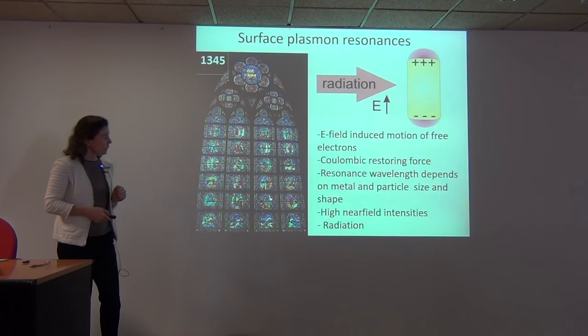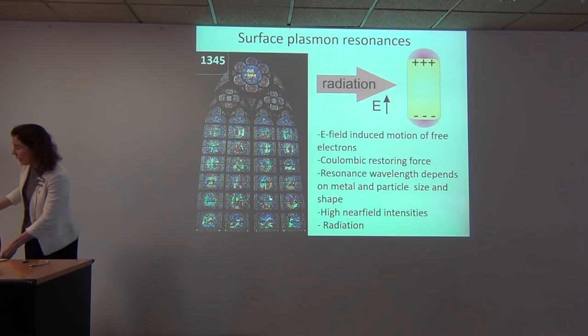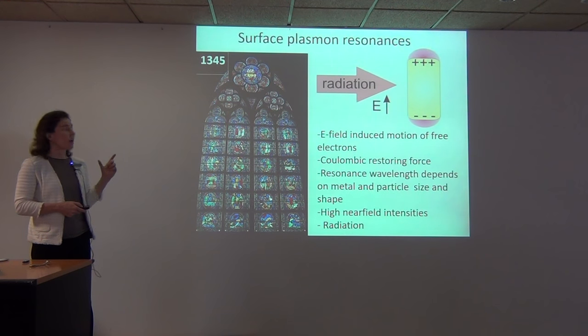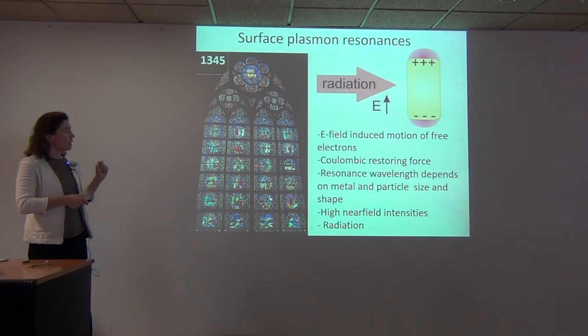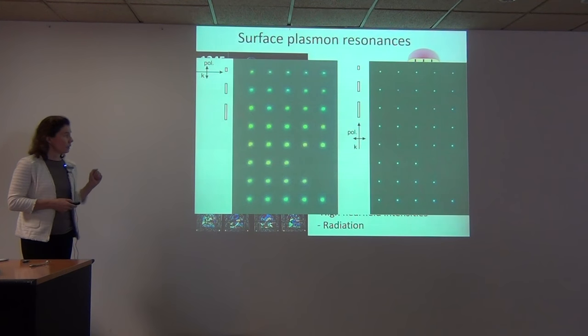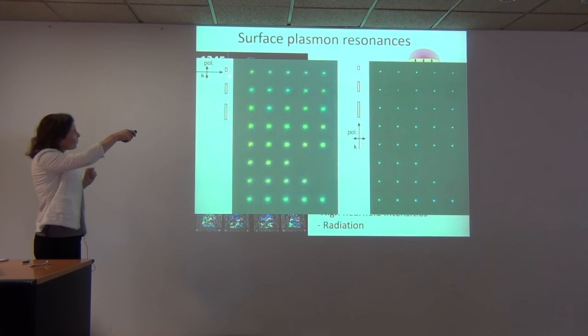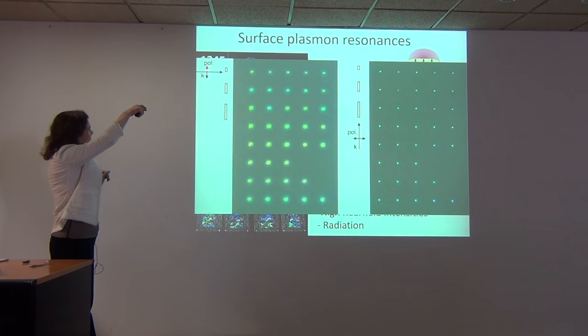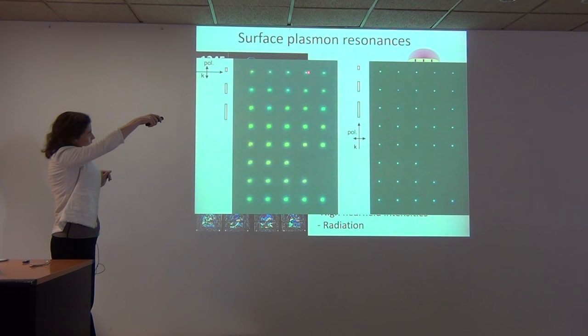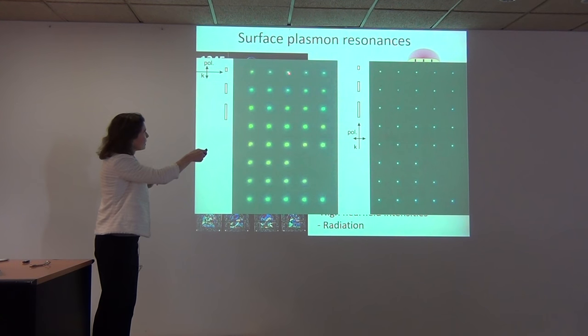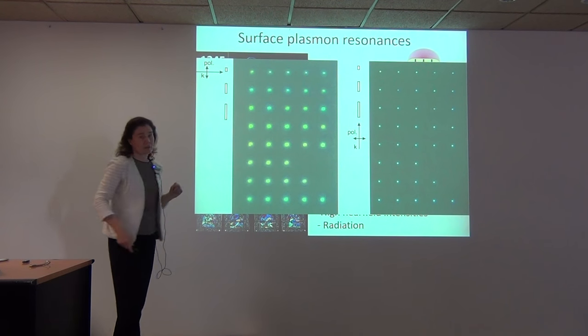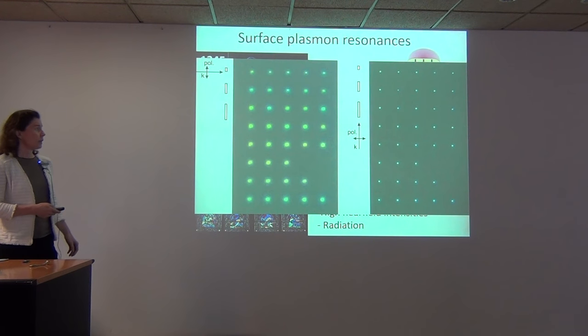They radiate quite nicely. This has been applied already for a long time because depending on the size, this resonance is a different color. So you can use nanoparticles of different sizes to create colors. Here you see this effect in a simple experiment where there are nanoparticles of different lengths but the same width. If you illuminate them with light polarized along the long direction, these have different sizes and consequently have different colors. If you turn the polarization so all particles oscillate in the short direction, the color is the same in all. So it depends on the size but also on the shape of the material.